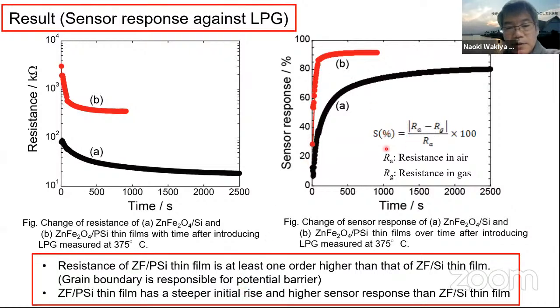The sensor response is defined using this equation, where RA is the resistance in air, and RG is the resistance in the gas. This graph shows that a steep initial rise is observed for the zinc ferrite film deposited on porous silicon substrate, and the sensor response is also higher. The sensor response for the zinc ferrite thin film deposited on the porous silicon is higher than that deposited on silicon substrate.